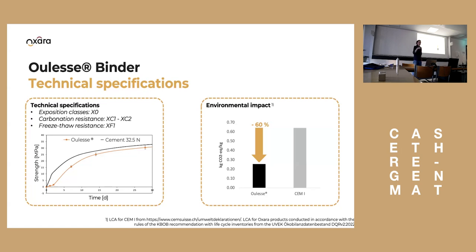For binders, one measures the carbonation resistance, meaning how fast they carbonate, how fast they lose their pH. In our case, the Oulesse binder has a lower pH and it does not comply with these carbonation limits that are given for applications where carbonation limits apply. That means that if you use a reinforced Oulesse, currently you have to use it in applications where corrosion is not happening because there is no moisture.